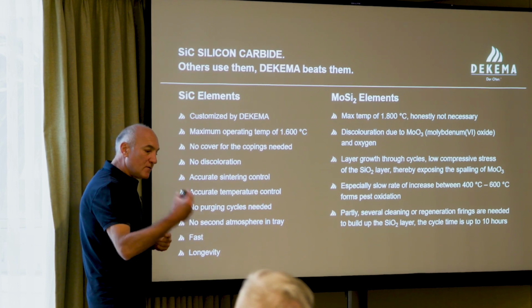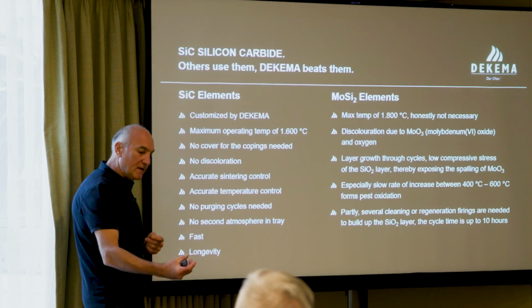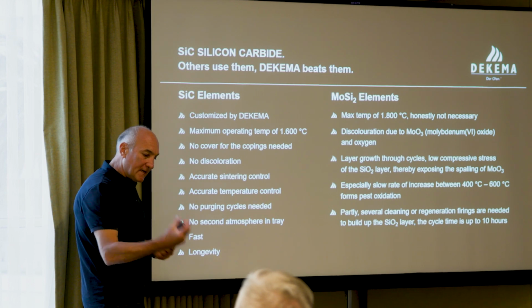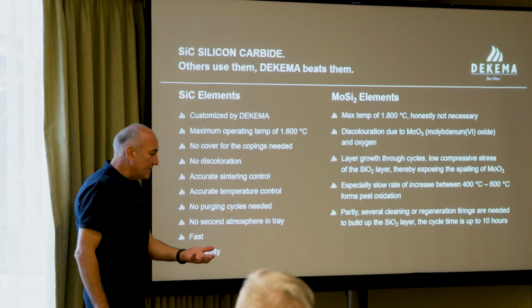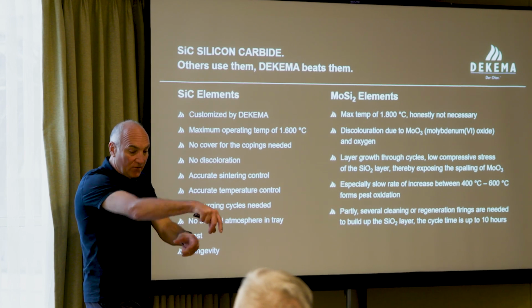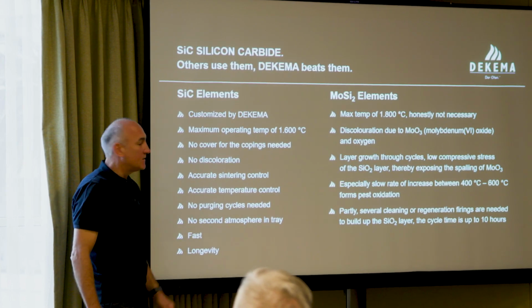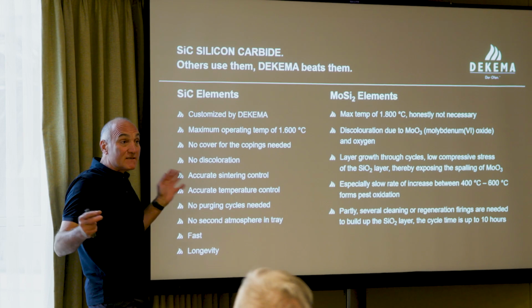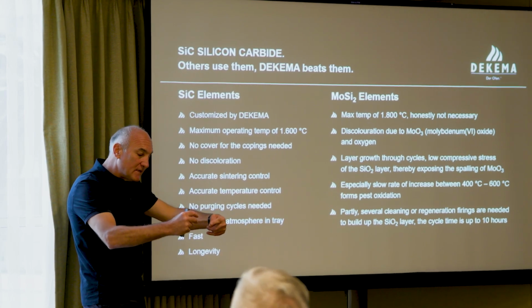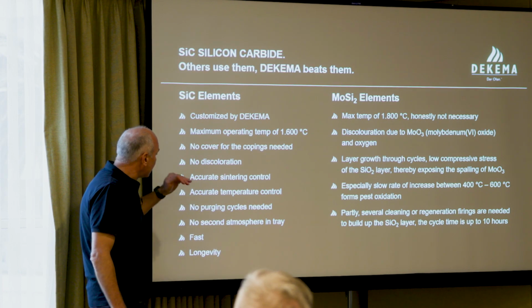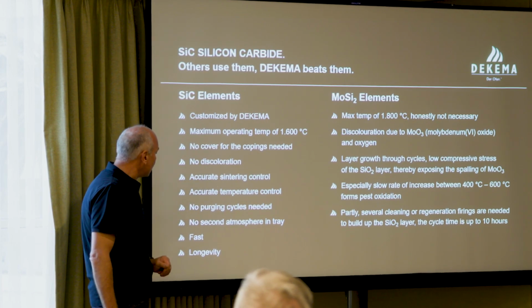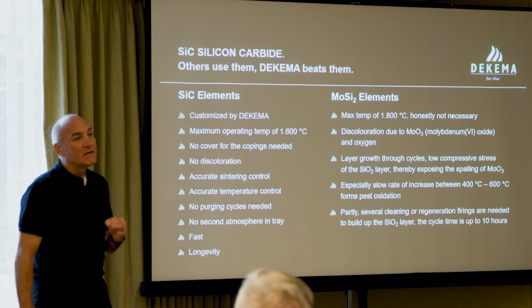No cover for the copings needed. What do I mean? If you don't want to have green or yellow stages of zirconia inside the furnace, you have to put it in a crucible, because then all the pollution cannot approach your zirconia. We don't need to do this. We can directly work with the radiation which is approaching the material. So we have an accurate sintering control, we have temperature control as we saw before, and we don't need purging.